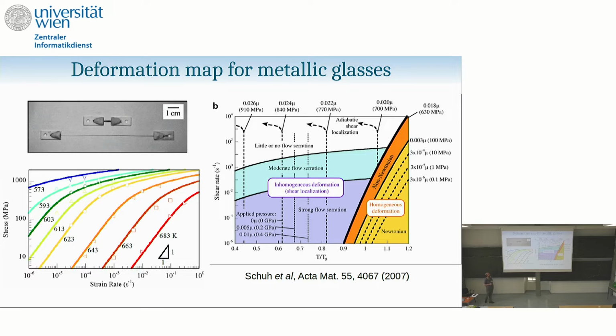What's interesting is that you can see here, as a function of strain rate and temperature, first of all, that these systems can be extremely ductile. They can also yield. Of course, you have some fragile rupture. They can show non-Newtonian rheology, and here you see flow stress versus strain rate curves showing shear thinning behavior. On this map you have two parameters, the strain rate and the temperature. At high temperature, at some point you reach the liquid regime, and you see some things which are not trivial in the relation between strain rate and temperature. At lower temperature, you are properly speaking in the glass.